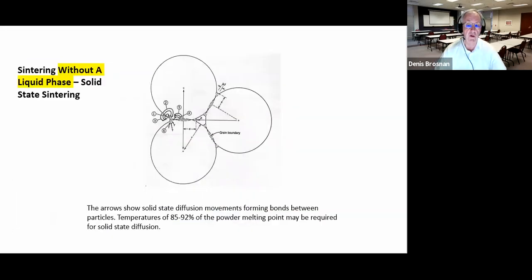And then here's the 3rd type, which is sintering with no liquid phase present. In this particular case, we still have the illustration of 3 spheres, or 3 circles, in contact here. But in this instance, while we have the high surface energy at points of contact, surface diffusion, movement of non-liquid phases, but atoms are going to move, particularly cations, along the surface. You can say they're going to jump along the surface or diffuse along the surface, and diffuse from inside the particles, inside the bulk, into this point of contact, and they're going to deposit new crystalline material at these points of contact. The reason that happens, again, is minimization of surface energy in the particles. So the driving force for sintering is that minimization of surface energy in order to consolidate the ceramic.